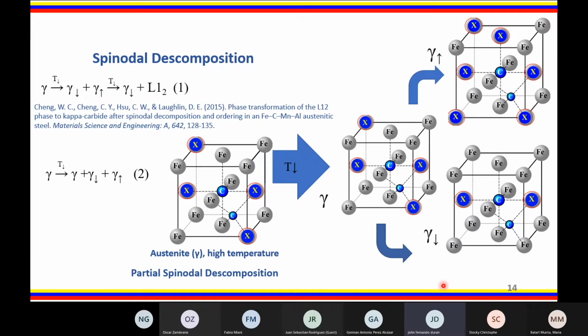The first equation represents the complete spinodal decomposition of austenite proposed by Cheng. In the second equation, you can see the partial spinodal decomposition of austenite that we propose in our paper. Thus, there are 3 austenites, 1 normal or initial, 1 rich, and finally 1 poor in solute atoms, as you see in the figure.